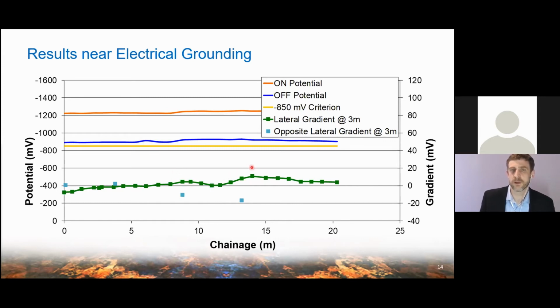And then I continue, and here's a little bigger coating defect on my pipeline, and maybe some extension of it here. Okay, so it appears that I've got a couple coating defects in my pipeline, but hold on. I've got my other side, my opposite lateral gradients. So what's happening is this means here I've got current in the direction towards my pipe. So I'm seeing current coming towards my pipe, but on the other side, it has the opposite sign. So my 0 is right here. So it's passing with the other polarity, which means the gradient, instead of coming to my pipe, is passing my pipe.